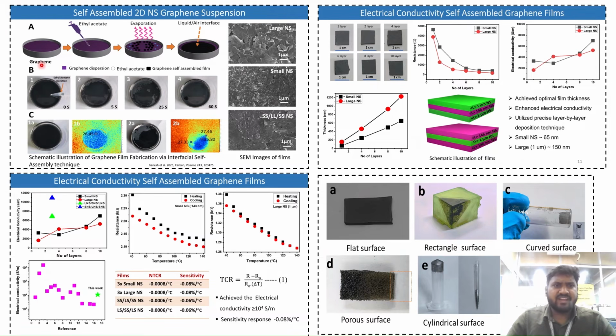Here we can see the schematic illustration of the interfacial self-assembly of graphene nanosheets, and we are seeing the temperature gradient here. About 1 degree Celsius change is taking place while the freestanding film is forming. Here we can see the morphology of well-aligned nanosheets of small, large, and sandwich structure. Here we optimized it and achieved layer-by-layer coating up to 10 layers and up to 1 micrometer.